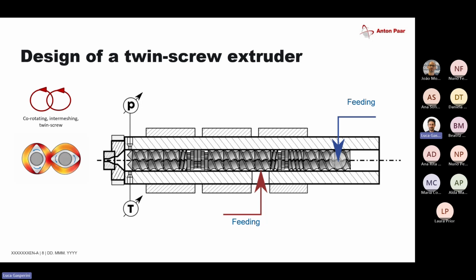This is one example of a screw configuration. The screw configuration is also a very important part of the whole process development. It's basically the most important part. Just to explain this one a little bit, right here the material is fed at 0D. It's simply conveyed to the top. Here the pitch is decreased, and by decreasing the pitch, you get a higher shear, a better mixing, but we also reduce the flow a little bit.